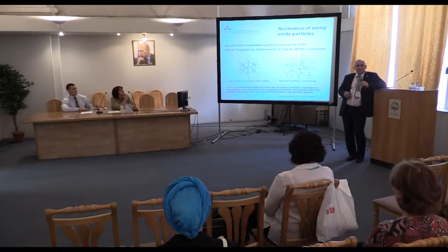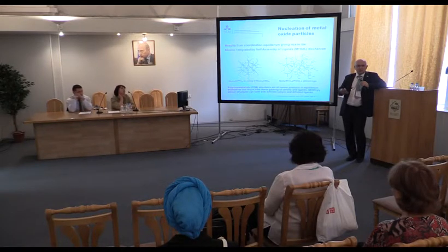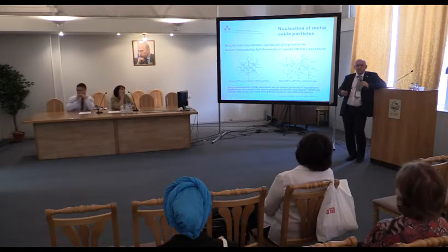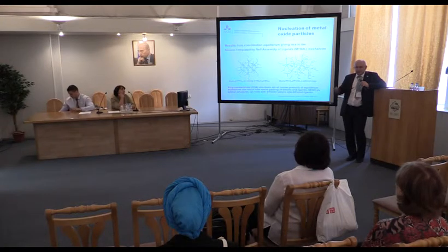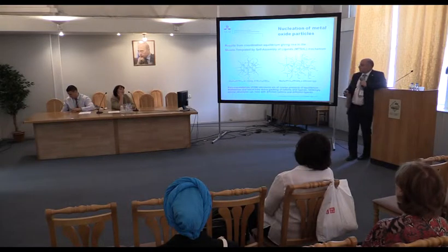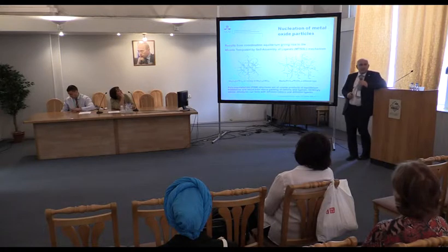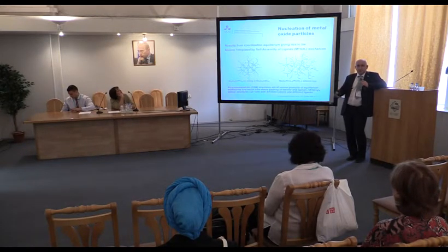Because clusters, what Albert Cotton, for example, studied, are structures which are very stable. They are so stable in solution that you can cook, for example, molybdenum sulfide clusters in concentrated nitric acid, and you only will replace some outer ligands, a given number of them. Of course, oxo-metallate constructions which are formed in the sol-gel hydrolysis of metal organic precursors are absolutely not like this. These are products of equilibrium at a given ratio between alkoxide ligand and chelating ligand and water.